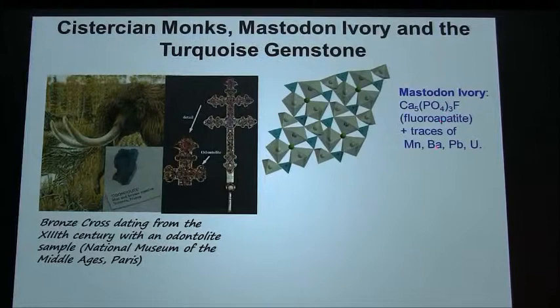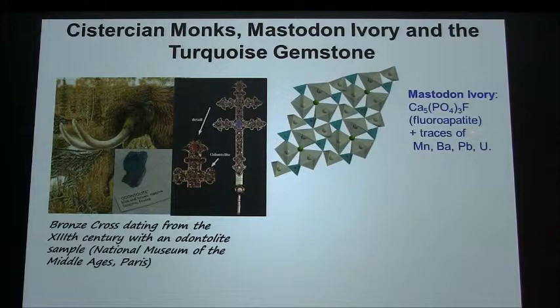It has a calcium phosphate structure, which we call apatite, which is what our teeth are. Again, the teeth composition is very similar. That's why we apply fluorine to our teeth, to help prevent cavities actually. But when you have traces of manganese or other transition metals, they can induce colors. In fact, this is the structure of the mastodon ivory.